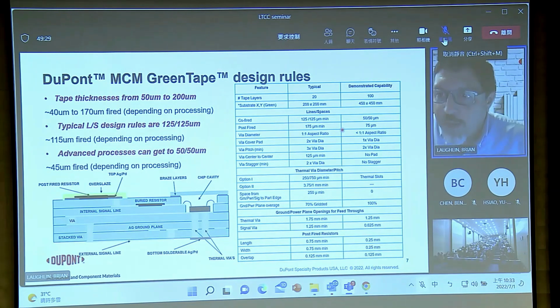And I'll talk in a couple minutes about how that's the widest, most general design rule. But the advanced processes, if you wanted to go with a lot of care and a little bit more expense in your screen printing or your patterning, you could get down to 50 micron line spaces, so something about 45 microns fired. And again, I show a cartoon cross-section of all the things that you can do. So you can make internal lines that turn into capacitors because they're parallel, or you can make internal ground planes, or you can make internal signal routing. You can even put resistors on the top and have an overglaze for environmental protection. You can make thermal vias, and you can make cavities for ease of wire bonding for chip carriers.